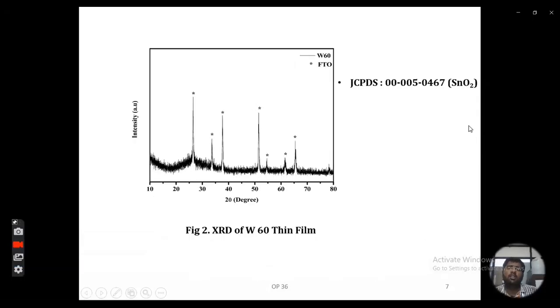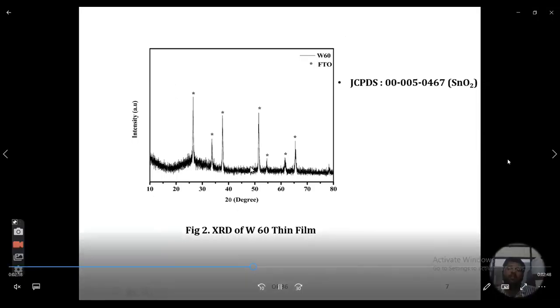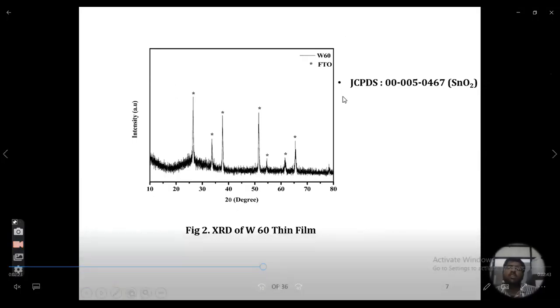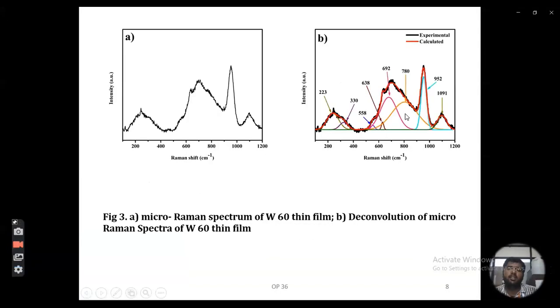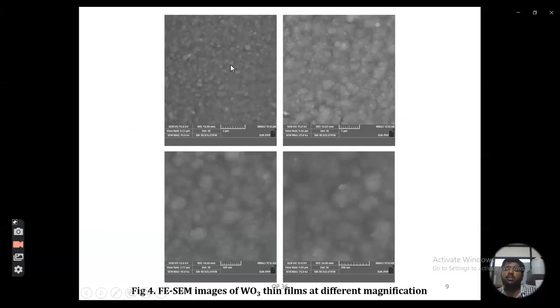Then, in order to confirm the phase of the WO3 thin film, XRD was carried out. From the diffraction peaks, it is clear that the WO3 thin film is in an amorphous phase. The diffraction peaks recorded here can be assigned to the FTO peaks, which were compared with the JCPDS card. Then, in order to further confirm the amorphous nature, the stretching of the W-O bond at 952 Raman shift confirms the amorphous nature of the WO3 thin film. Then, uniform nanogranular morphology was revealed through FESEM images at different magnification.